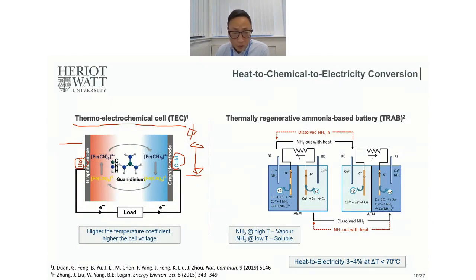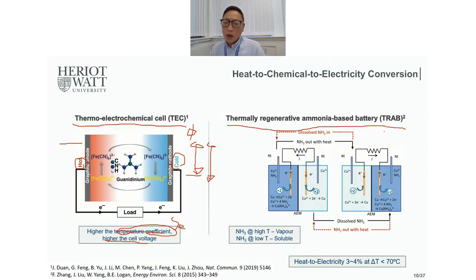As I noted here, the higher the temperature coefficient, the higher the cell voltage. The temperature coefficient in this case is the same as the Seebeck coefficient. So the higher the Seebeck coefficient, the higher the potential shift across the range of the temperature gradient. The other type is the thermally regenerative ammonia-based battery.